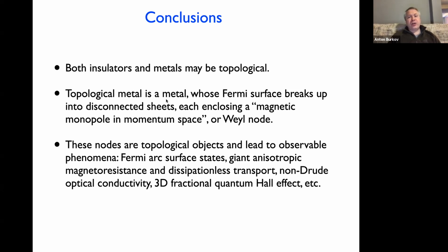So this topological metal is a metal whose Fermi surface breaks up into disconnected sheets, each enclosing a Weyl node, which acts basically as a magnetic monopole in momentum space. So these nodes are topological objects and they lead to observable phenomena. There are Fermi arc surface states, which I didn't mention, which connect the projection of the Weyl nodes on the surface Brillouin zone.